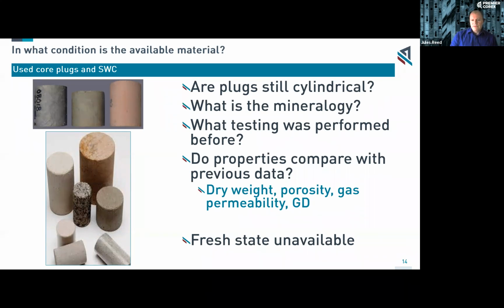But of course, with these routine core plugs, the one measurement that you are always unable to make is fresh state analysis. Because with fresh state, it can only ever be fresh once, and that's when we first obtain the sample from a core, take a plug from that core, and begin to use it directly after that core process.